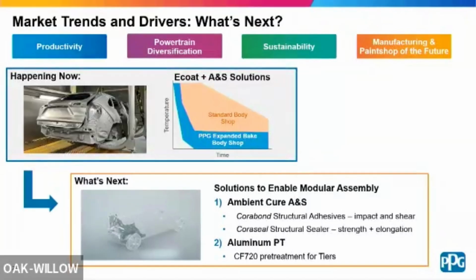Yeah, so for PPG, our focus generally for oven cured systems is on 1K technologies. There's a lot of simplicity in equipment, right? A 1K versus a 2K is a technology that's tried and true. We believe we can reduce the temperature and still get good performance. For an ambient cure though, now we are thinking 2K, and there's a lot of complexity there, right? In terms of new equipment, making sure you have the right mix ratios. But we believe that with 2K you have a little bit more control over the reaction than you would with a moisture cure 1K, for example. So I see 2K more for an ambient cure type technology system, which would be for maybe a more disruptive manufacturing practice, or if you need more plastics on your line. So I think that's where we would position our portfolio. Hopefully that answered the question. But Paula, anything else to comment?